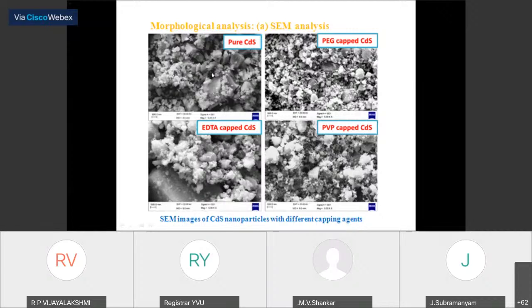When you observe the micrographs for the three capping agents, this one is the cadmium sulfide without any capping agent. This is the cadmium sulfide nanoparticles with the PEG capping agent, this is the cadmium sulfide with EDTA, and this is the cadmium sulfide with PVP. What you can observe here is that the cadmium sulfide prepared without any capping agent has agglomerated particles, and all the particles are very big in nature.